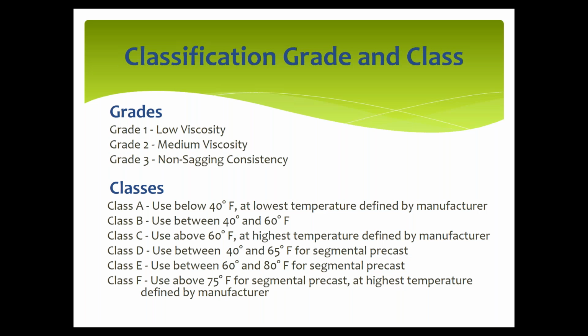For the grade, we have three grades. Grade 1 is low viscosity, Grade 2 is medium, and Grade 3 is non-sagging consistency. In terms of classes, we have A, B, C, D, E, and F. Class A is used below 40 degrees and the lowest temperature defined by the manufacturer. B is used between 40 and 60 degrees Fahrenheit. C is used above 60 and at the highest temperature defined by the manufacturer. D is used between 40 and 65 in segmental precast. E is between 60 and 80 for segmental precast. F is between 75 for segmental precast and as high as the temperature defined by the manufacturer.